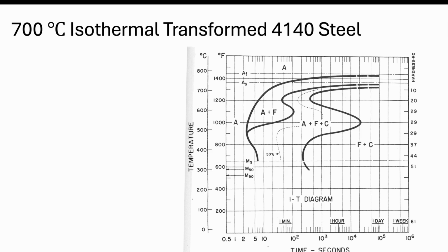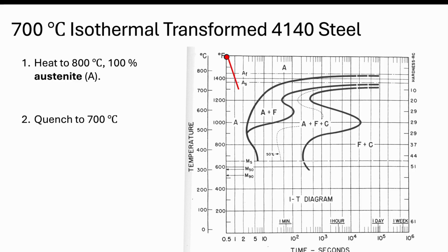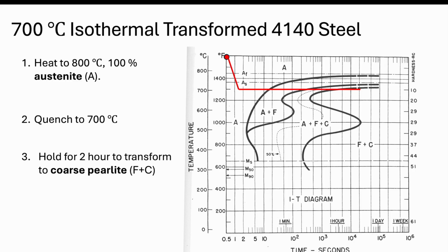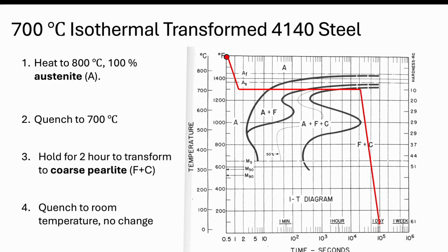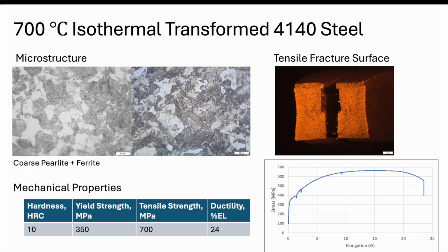So 700 isothermally transformed. Again, we heat up to 800 or above, hold there to get austenite. We quench down to 700. Here we're going to hold for around 2 hours, and we're going to get coarse pearlite. And again, coarse pearlite plus ferrite. So what do we get? So these are our microstructures for 700.